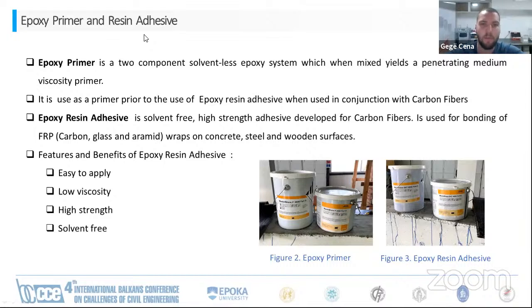Epoxy primer is a 2-component solvent-less epoxy system which, when mixed, yields a penetrating medium viscosity primer. It is used as a primer prior to the use of epoxy resin adhesive when used in conjunction with carbon fibers. Epoxy resin adhesive is a solvent-free, high-strength adhesive developed for carbon fibers. It is used for bonding of CFRP wraps on concrete, steel, and wooden surfaces. Features and benefits of epoxy resin are that it is easy to apply, low viscosity, high strength, and solvent-free.